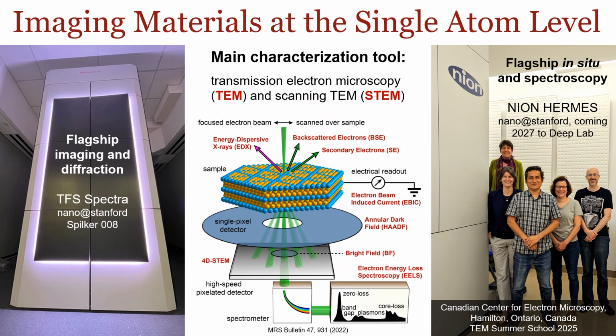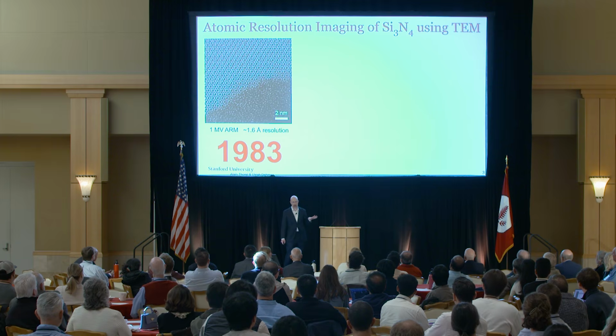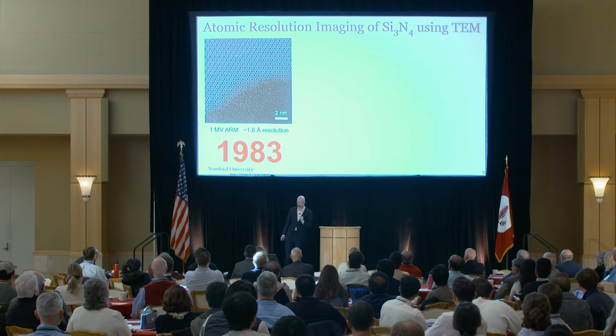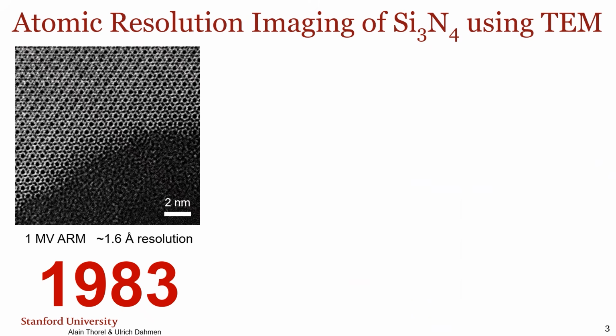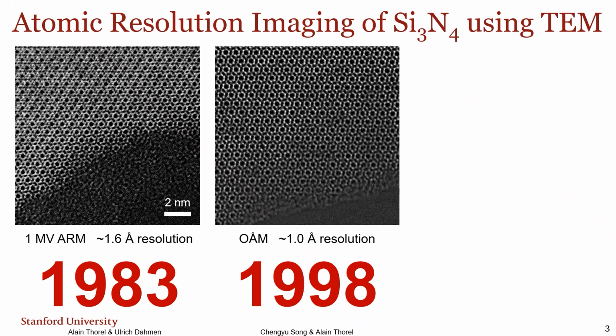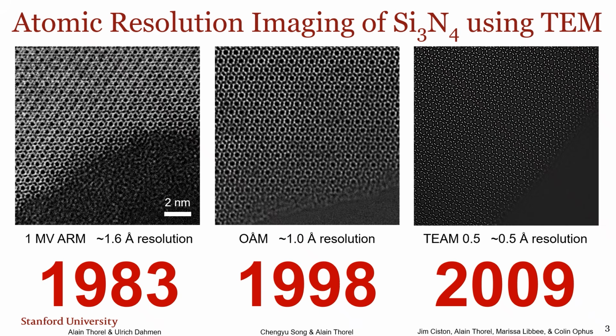And this is just a photo of me visiting the Canadian Center for Electron Microscopy, where they have a very similar instrument here. Okay, so let me give you a brief history of electron microscopy and atomic resolution imaging. So this is an image from my birth year, actually, showing silicon nitride down to essentially lattice resolution, about 1.6 angstroms. And after another decade and a half of research, we were able to push the resolution down to about the 1 angstrom level. So you can see it's a sharper image of this hexagonal lattice, but this is not the ground truth of the sample. It wasn't until the newest generation of microscopes, like the Spectra I showed you, that we were able to see the actual ground truth of this sample.